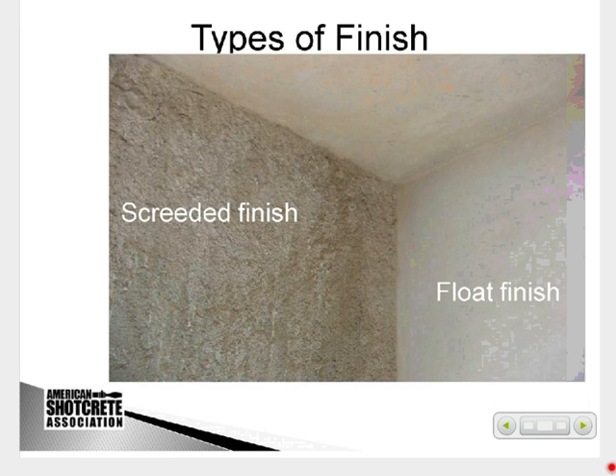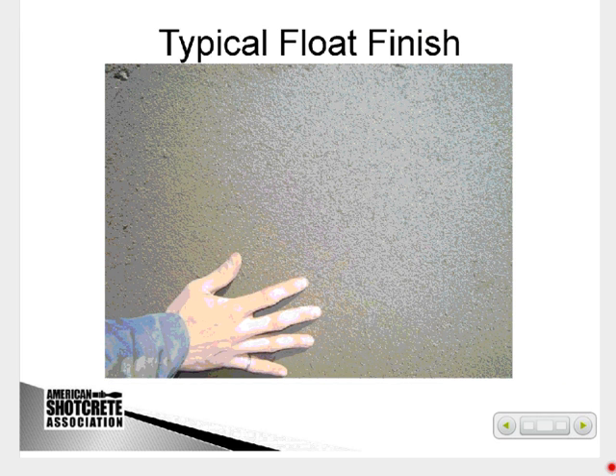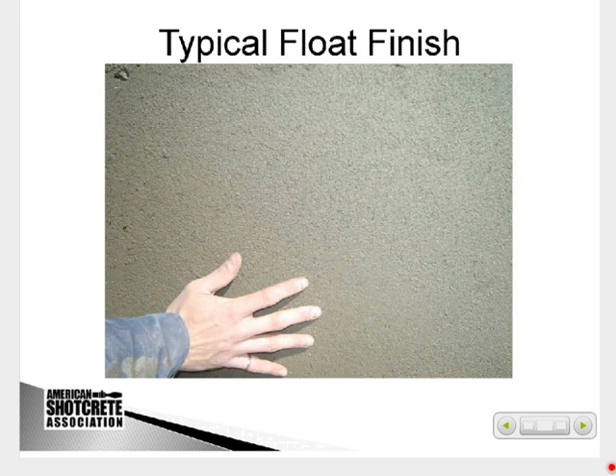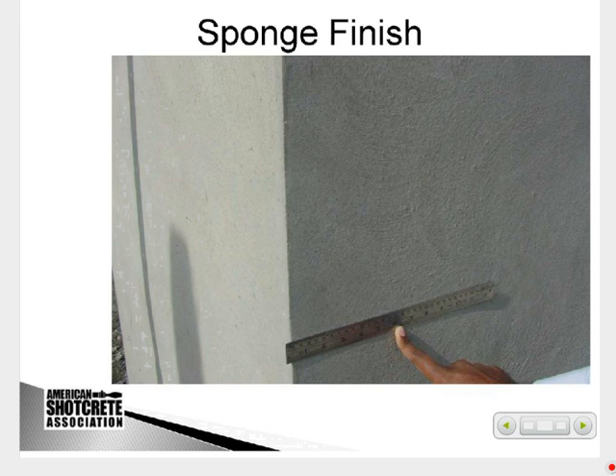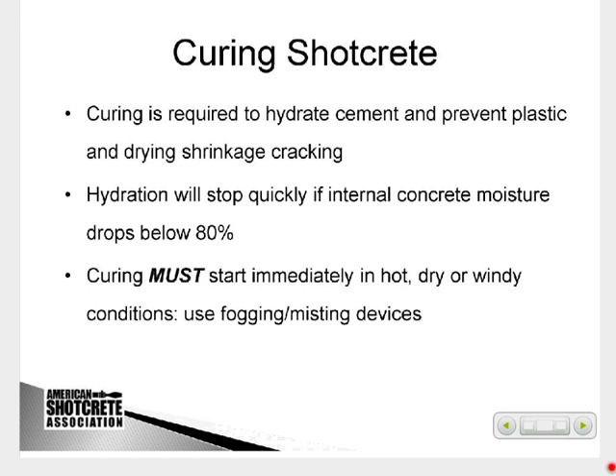This is a representation. We can do float finishes, a screed finish. Basically, you shoot it, you screed it, and it gives you a nice flat tolerance on your thickness. Here's a typical float finish, very similar to what you can get with a plaster wall. Sponge finish. And we can actually do hard trowel finishes. If it's an outdoor exposure, we tend to not recommend hard trowel just because of freeze-thaw resistance. But it is something that we can do if required by the architect. Curing, because we have an exposed surface, it's important to cure, especially in hot, dry conditions.